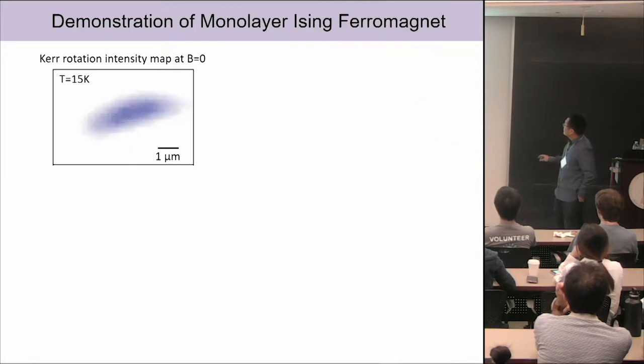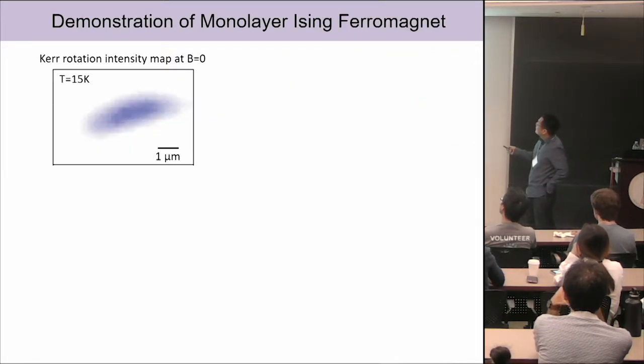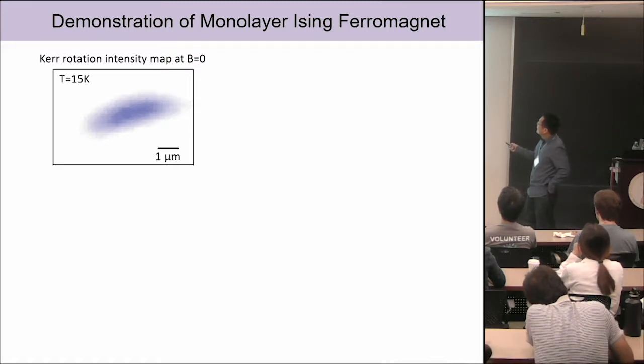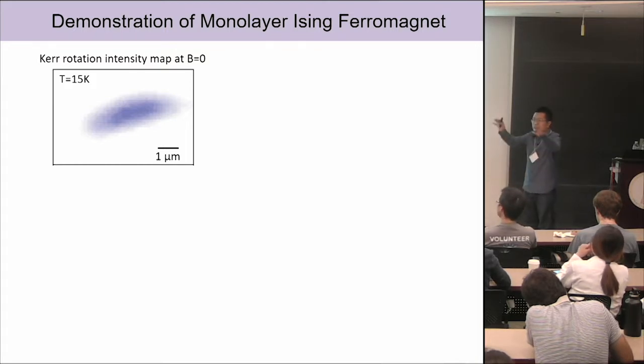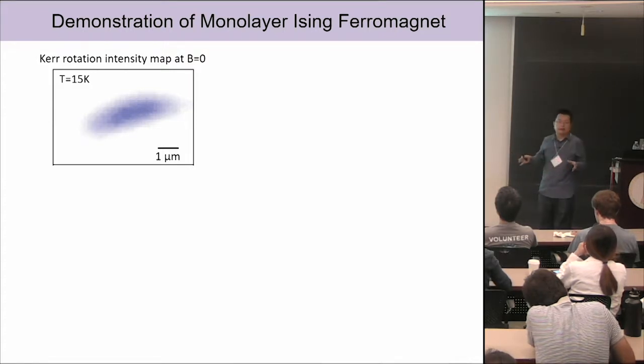Then we just go directly to the monolayer. What I show you here is the Kerr rotation intensity map without applying a magnetic field, and the temperature is 15 Kelvin. Basically, we just cool down the sample and do nothing else. Then what I show you here is a map, right? You already see there's a homogeneous Kerr rotation signal across the sample. It indicates we do have ferromagnetism in this monolayer.